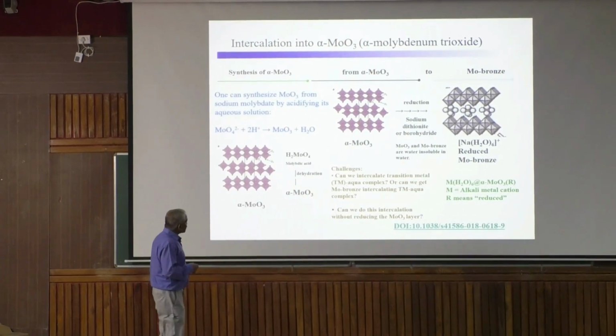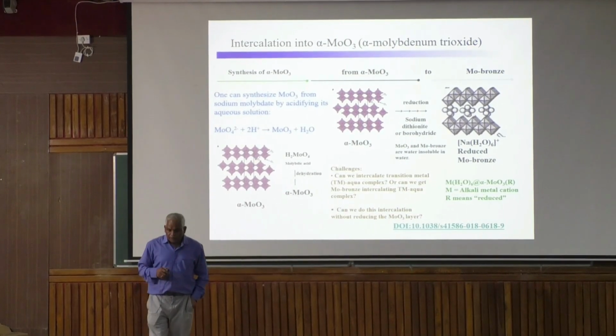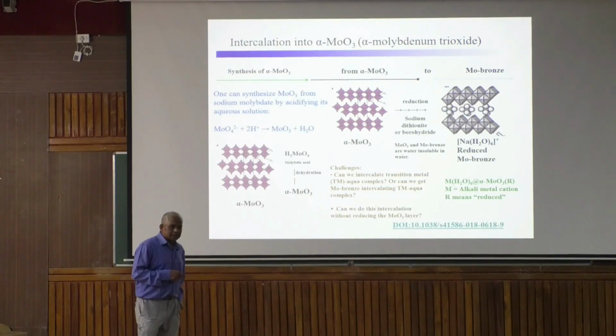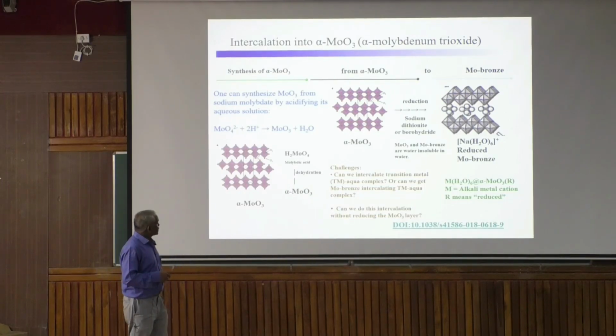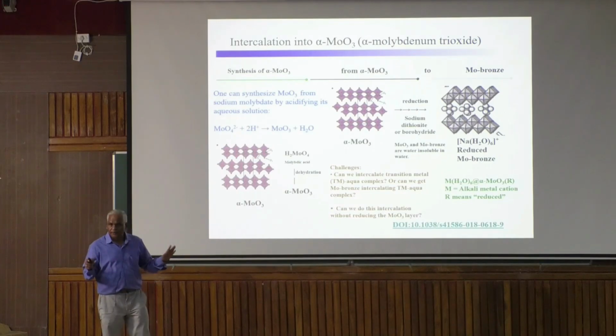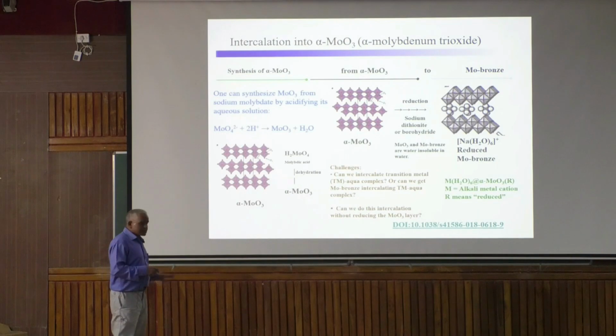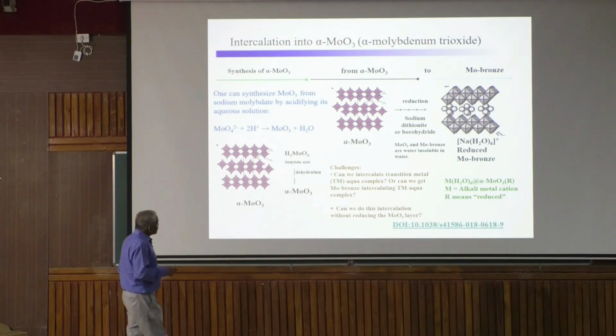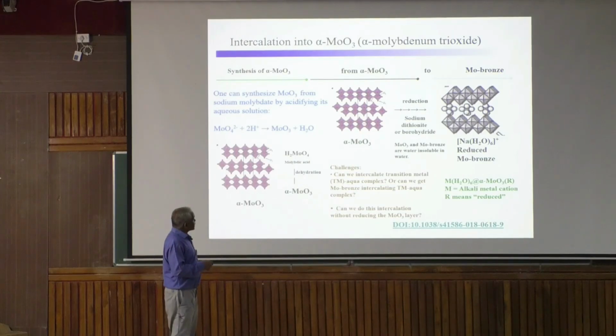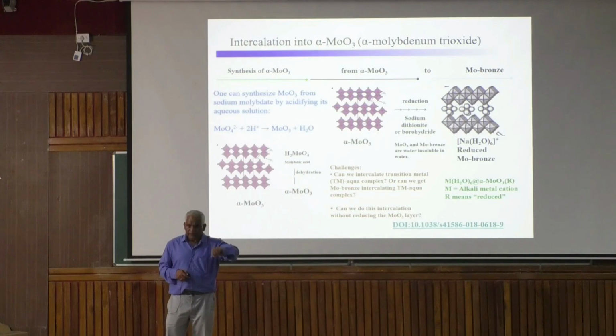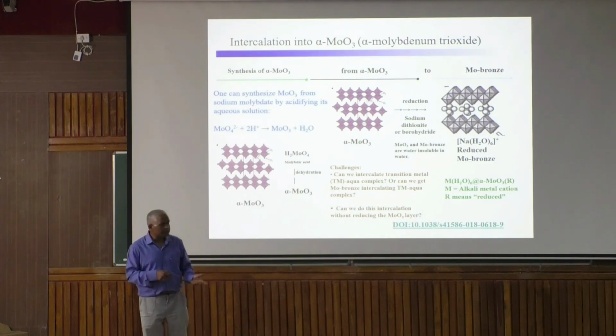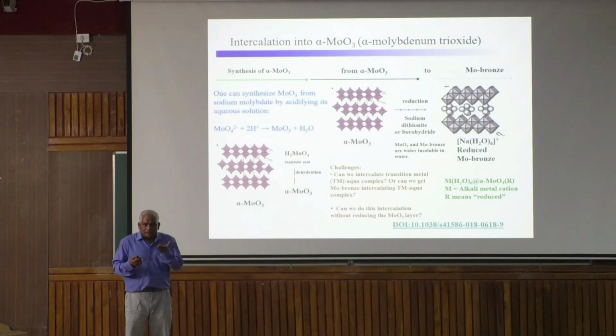Let me also tell you in this context about something called molybdenum bronze. Molybdenum bronze you find in a textbook-level inorganic chemistry book. It was discovered in Germany more than 100 years ago, in 1896. What is molybdenum bronze? This MoO3 is a water-insoluble neutral molecule, no? Molybdenum is in the plus 6 oxidation state, and every oxygen is 2 minus, so 2 minus 2 minus 2 minus, minus 6, so a neutral molecule. It has an extended layered structure, like graphite, neutral. If you put it in water, you get a suspension. That means every MoO3 compound is water insoluble. Now, if you reduce the suspension with sodium borohydride or sodium dithionite, a reducing agent, immediately you get a very nice red-brown lustrous color. That means something happened. What happened?